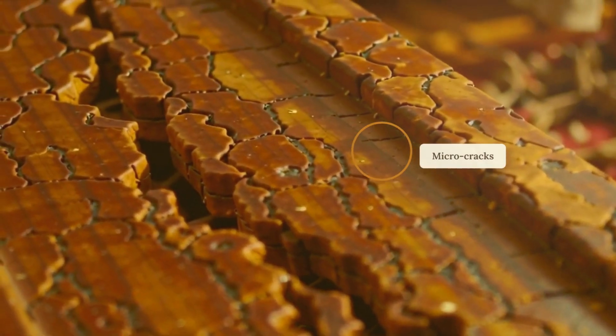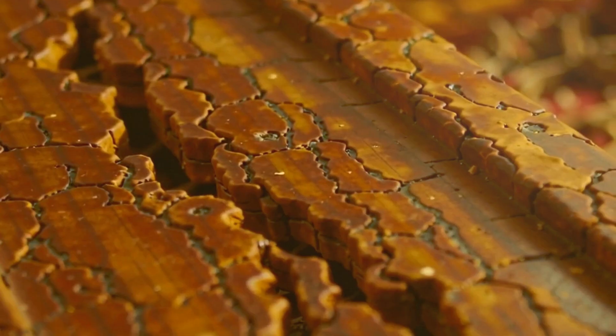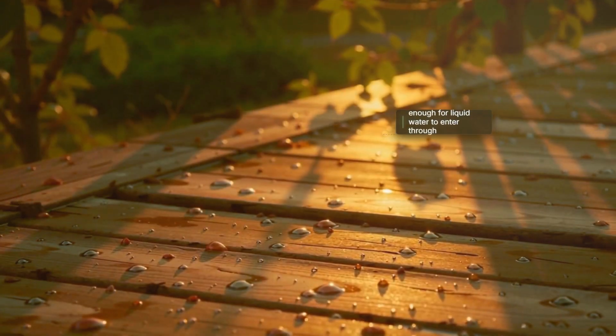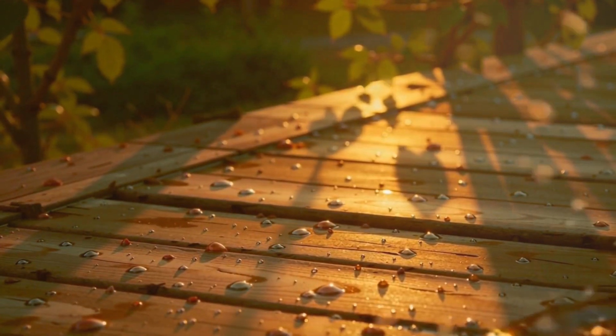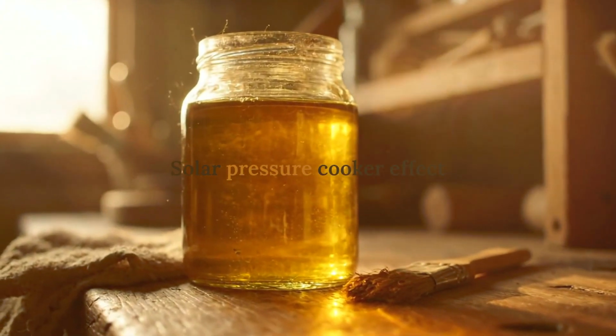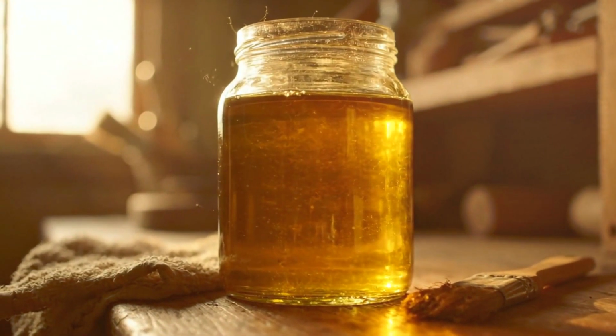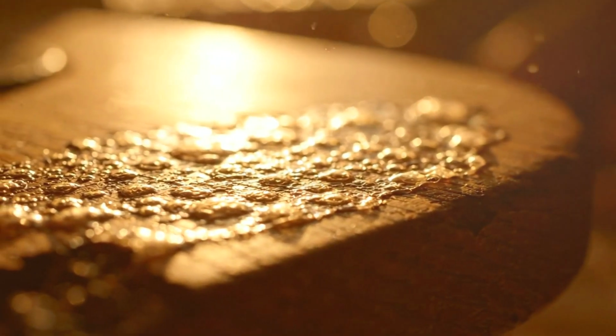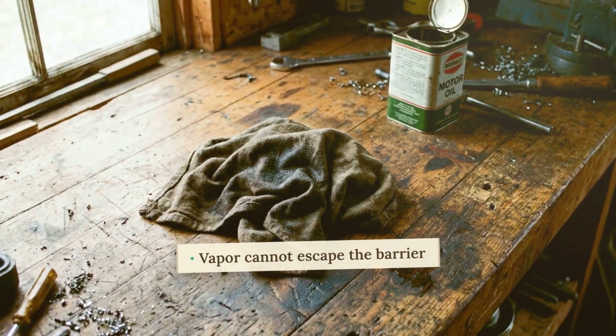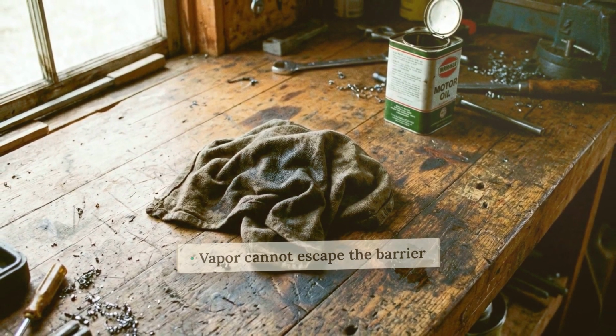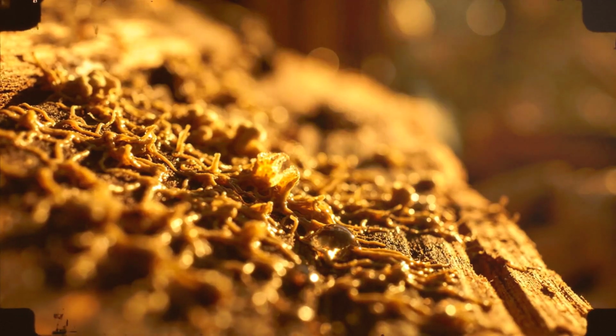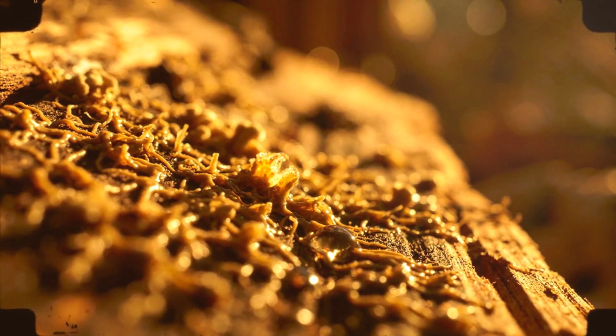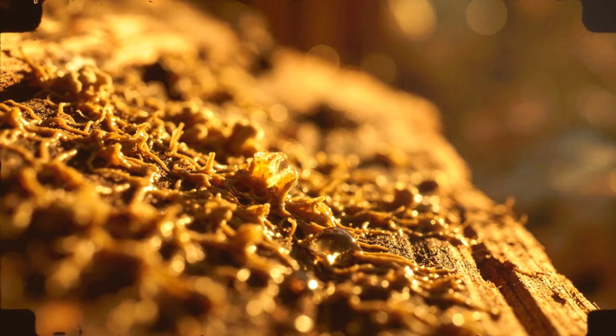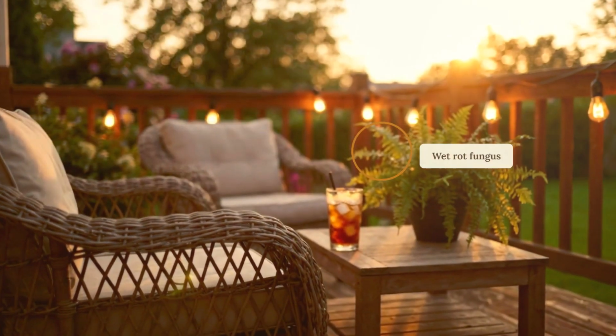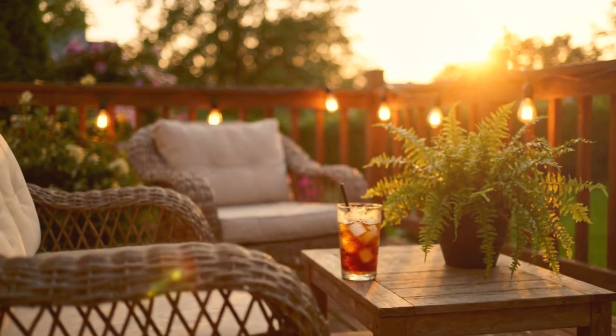Microscopic hairline cracks form along the grain lines, cracks too small for your eye to catch, but wide enough for liquid water to enter through capillary action. Once water creeps underneath that rubbery film, the synthetic coating turns into a miniature solar pressure cooker. Sun beating down on the deck heats the trapped water, converting it into moisture vapor that cannot escape through the impermeable plastic barrier above. The internal vapor pressure spikes, breaking down the lignin, the organic glue holding wood fibers together, and creating an ideal, high-humidity anaerobic environment for wet rot fungus to feast on the structural sugars inside the board.